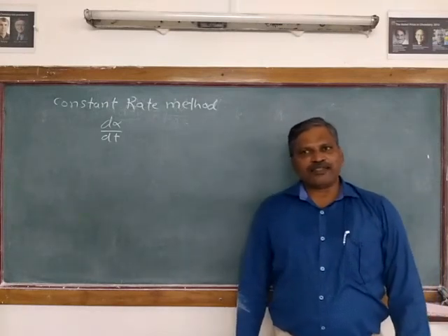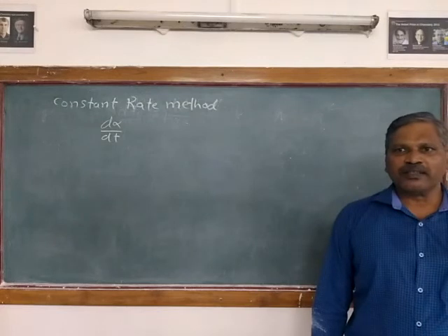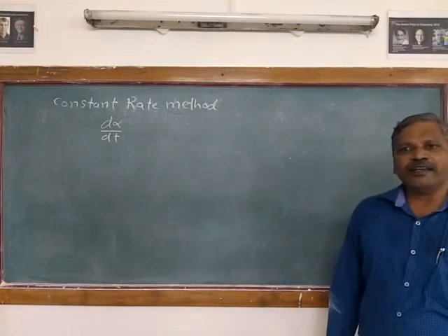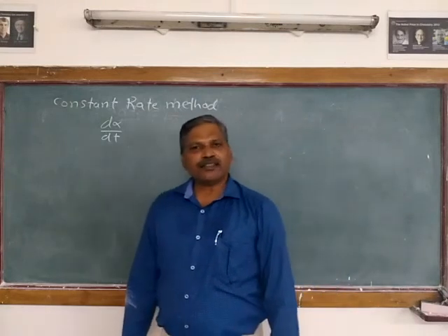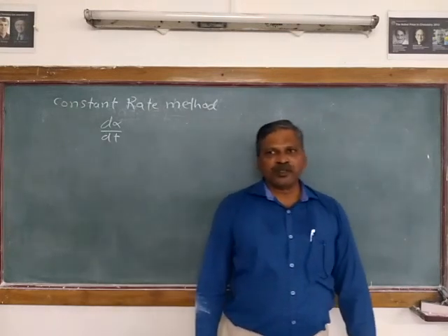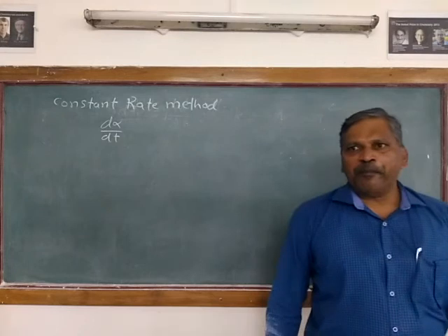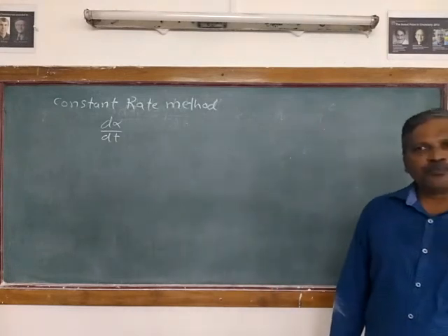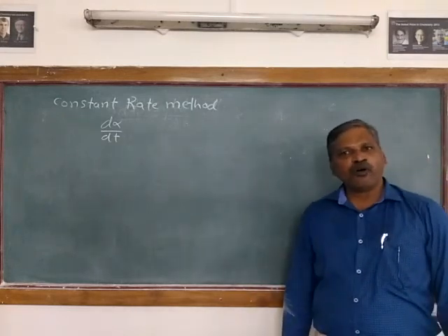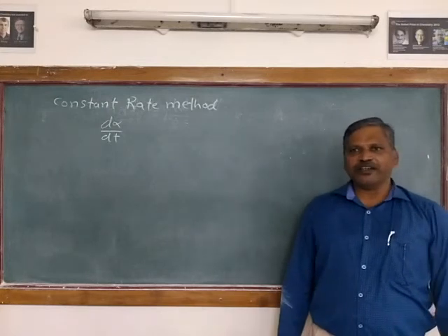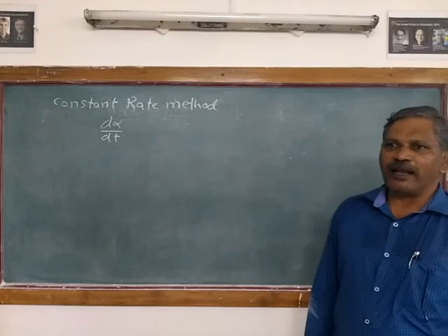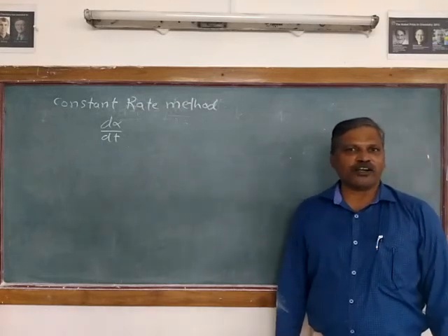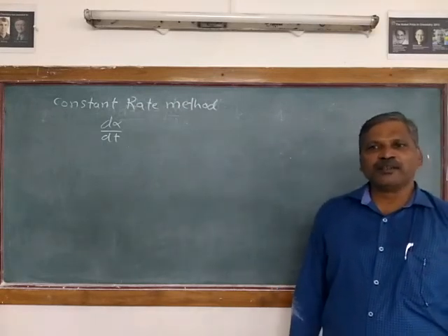Rouquerol is the name of the scientist who proposed that a quantity directly related to the decomposition rate is kept constant. This quantity may be the evolved gas flow, the thermal flow, or the DTG signal. This is the technique of constant rate thermal analysis, CRTA.